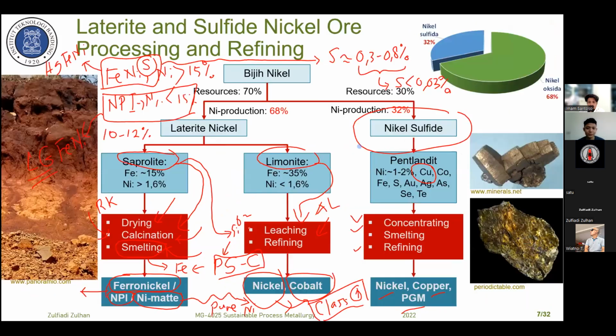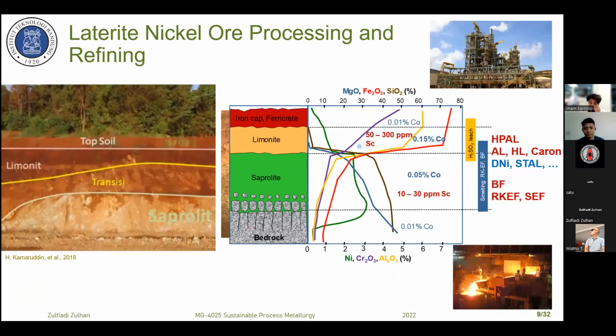So now we're back to the laterite nickel ore. If you see from the top, the concentration of the nickel, iron, silica, magnesia, alumina, chromite. You see here the top soil, also called iron cap. The iron content is in the form of Fe2O3. We see here the red line. The iron content could be close to 50%, more than 40%, in the iron cap.